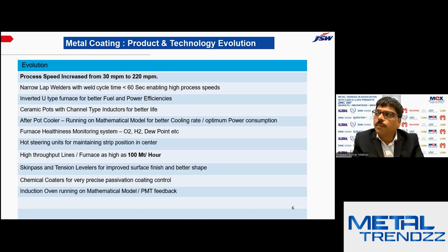Long back, around 3-4 decades back, only metal pots were used. Right now, those metal coating lines use ceramic pots with channel type inductors for better life. So this increases the utilization of the overall metal coating line. We have furnaces operating at 100 tons per hour. Initially, it was only 5 tons per hour. Right now, it is 100 tons per hour. We are able to introduce skin pass and tension leveler in our process to improve the surface finish and shape. And we have done a lot of innovations in terms of mathematical models to control the process parameters.